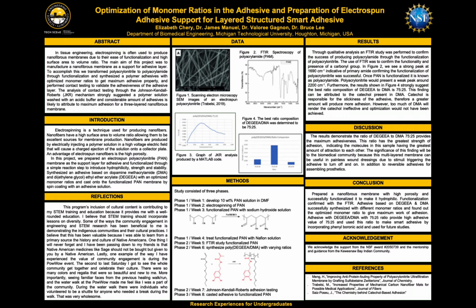So we did that by running an IR spectrometer. And essentially what that does is there's going to be infrared radiation transmitting and producing frequencies, and this will be recorded onto a spectroscopy graph. And on that graph, there will be peaks that are broad or sharp or weak. And specifically, we were looking for a sharp peak at 1690, and that is what we got. And this is indicative of a primary amide group being present. So with the IR spectroscopy, we were able to confirm that the functionalization was successful and the primary amide was produced.